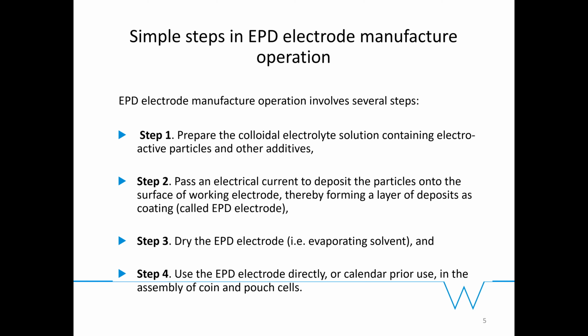And also, finally, step 4 is you can either use the electrodes as they are after they're prepared, and they can give reasonable performance, or you can calendar them, like hot pressing or cold pressing, to ensure better electrical contacts between the electrode surface and the aluminum foil, and you can usually get better performance by calendaring. So all these will be discussed in the supercapacitor part of my talk.